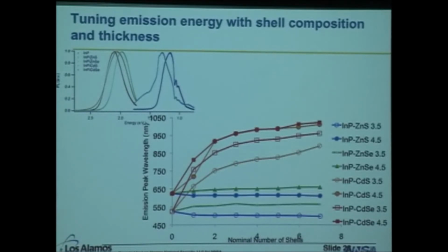And this, along with lifetime studies that we've done, is clearly an indication that we've gone from a quasi-type 2 to a truly type 2 system. And it's these orange guys that are giving us the non-blinking behavior so far. We haven't looked at the cadmium selenide-based ones, but with the zinc, we can actually keep in the visible region, which for certain applications is nice.